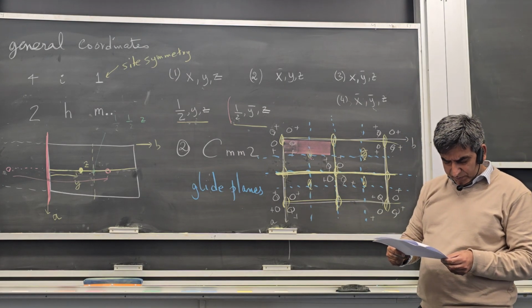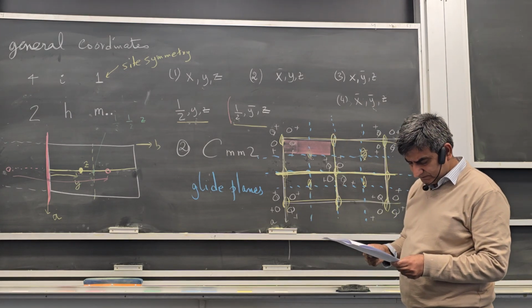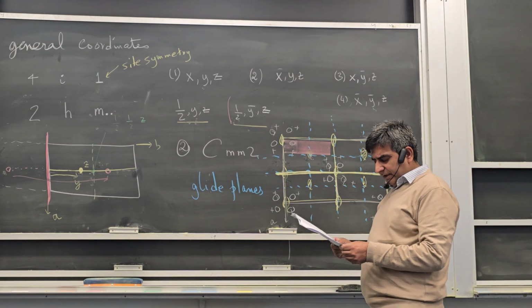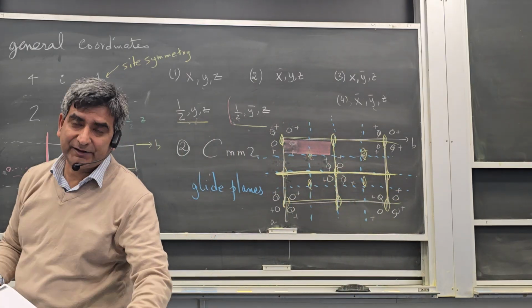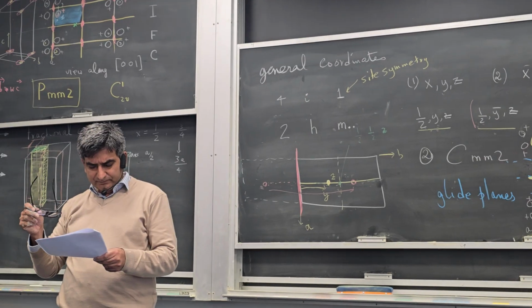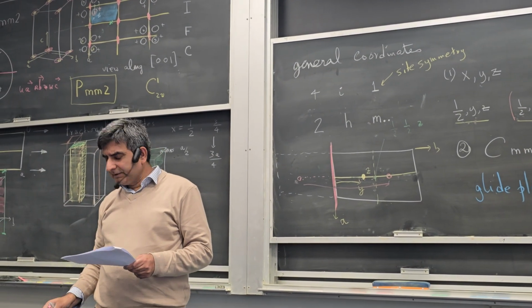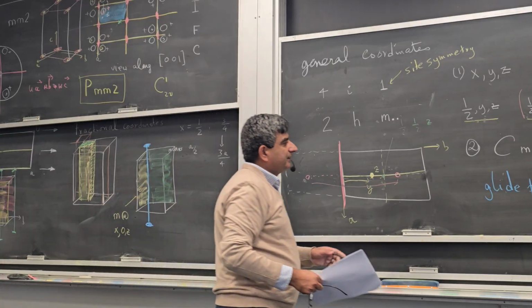Now, the symmetry operations are of two kinds. This is something really important. There are two sets of points. The lattice, since it's C-centered, has 2 points within the set. One is at the edge, 0, 0, 0, and the other is at half, half, 0, which is this point over here.